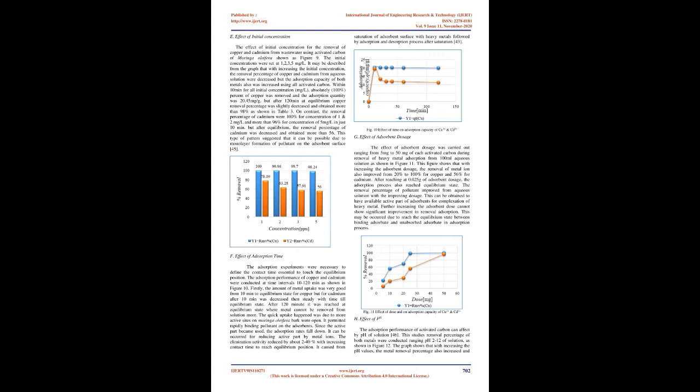The Freundlich plot and the Langmuir plot fitted favorably well with the isotherms because the value of RL obtained from the slope was 0.0021 for copper and 0.22 for cadmium, favorable when 0 < RL < 1. For the Freundlich isotherm, a value of n, 4.22 (greater than 1) for copper and 1.91 (greater than 1) for cadmium, is favorable when 1 < n < 10, and represents a favorable condition following the work of McKay and Ho, 1998.